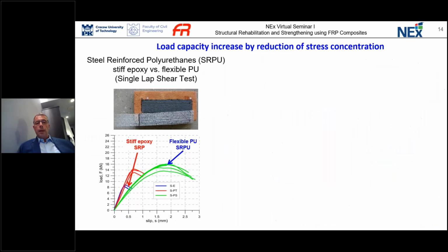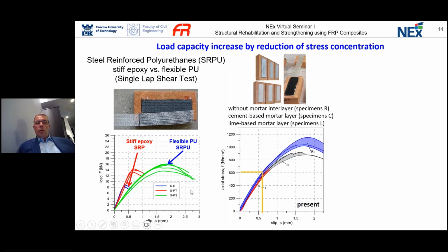So also when we compare steel reinforced polyurethanes, I mean that in this case we have steel fiber bonded with polyurethane flexible matrix, and we compare it with stiff adhesives, you can see clearly the behavior of this system. If we increase the stiffness of the polyurethanes, we receive a higher value, but of the same stiffness. But when we apply flexible polyurethanes, we receive much higher ultimate load than in the case of stiff epoxy resin, and also very high damage energy. This is the area under this curve. What is also tricky, if we use some composite materials in buildings, masonry buildings, in this case we have plasters.